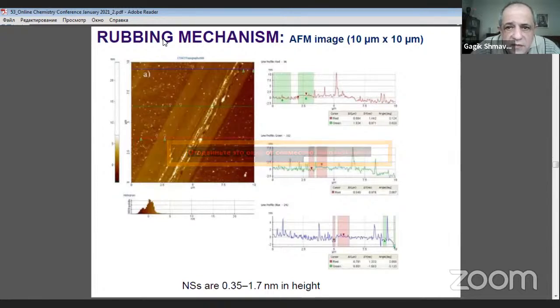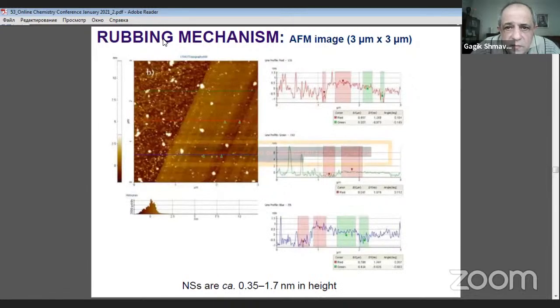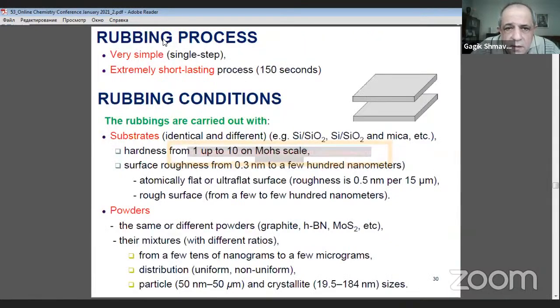Here you can see AFM images of these nanostripes at different scales. We also measured IV characteristics of these mono and multi-layer graphene nanostripes, and you can see that there is a big difference between monolayer and multilayer graphene nanostripes in IVs. For the rubbing mechanism, you can see a TEM image, and you can clearly see the structure of graphene stripes, graphene sheets.